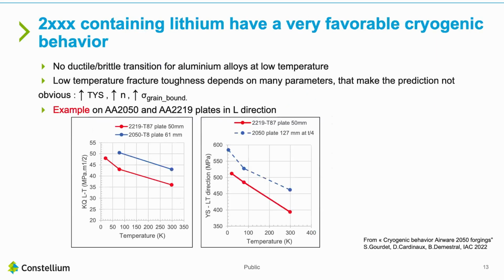At cryogenic temperature, 2,000 series also exhibit good behavior. It is known that the yield stress increases when temperature decreases. It's more difficult to predict the evolution of toughness because it depends on many parameters. The TYS increases, but also the strain hardening, and the stress on grain boundary is also modified at low temperature. For this alloy, we observed both an increase of yield stress and toughness when the temperature is decreased down to cryogenic temperature.